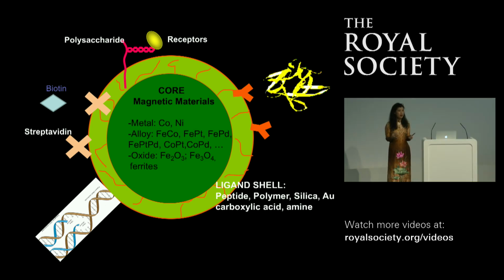You don't want them to aggregate, because we know gold nanoparticles, gold nanorods, when they aggregate, they change the optical property. Later on, I will show you the slide. When magnetic nanoparticles aggregate, they also change their magnetic property. So you need to be able to functionalize them with a different kind of molecule, and that molecule then has a specific binding to the intended application, okay?